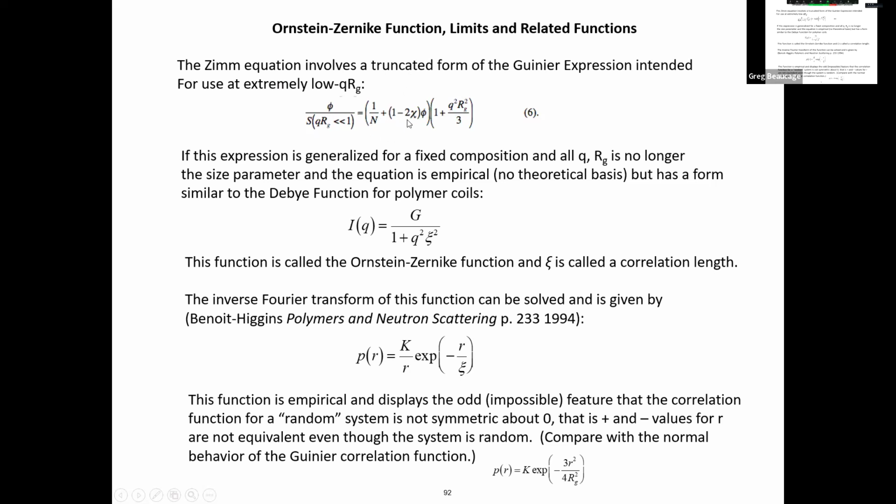Okay, so this Zimm equation becomes one of the fundamental equations to look at. And also one of the most mysterious equations because people don't understand where it came from. Like, what is this thing? It's not really explained anyway. So you just have the Zimm plot. To linearize the data, you're going to get the Zimm plot, which is going to be this weird thing: concentration over the intensity, versus some other factor, like the contrast factor, and then versus Q squared plus concentration times a constant.